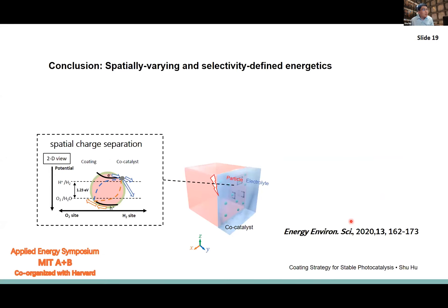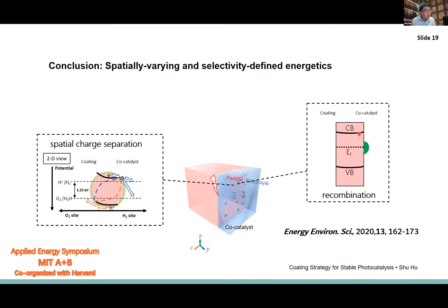To summarize: achieving efficiency in a photocatalyst requires renewed thinking. The three-dimensional picture of the solid-liquid interface shows there is an electrical field arranged laterally along the interface — between the reductive and oxidative sites — that is sufficient to drive charge separation. We must maintain this arrangement. If selectivity cannot be controlled, the energetics of the co-catalyst will make the overall energetics symmetric again, resulting in recombination.